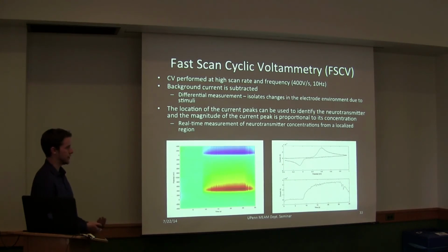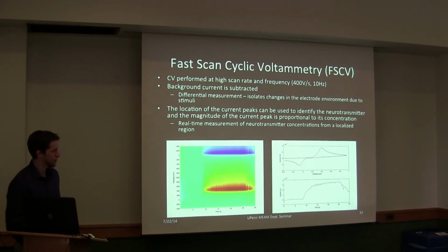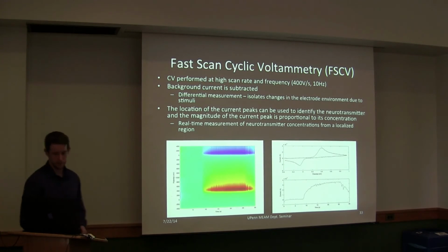Typically the peak location is dependent on the kinetics and the nature of the reaction, and you can look at the current at the peak. So you can take a line across this cross-section, look at the current over time, and get a map of the concentration over time. This was with the CNP in a flow cell, where at about 10 seconds we turned on the dopamine flow. Then it ramps up and hits some steady state concentration. At around 25 seconds we turned it off, and it starts to drop back down. So you can do real-time measurement of neurotransmitter concentrations for cellular studies from a very localized region of cells.